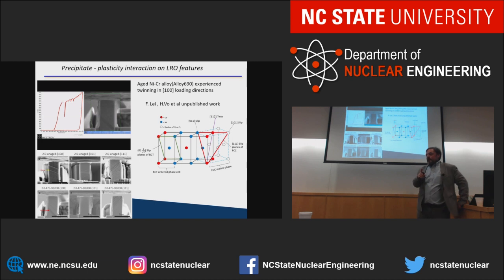Now that's not slipping, that's twinning. The crystal lattice changes by 60 degrees, changes the contrast, and you see that here in the still images too. You actually see the formation of twins, not these slip steps, which is different. So it turns out that if you compress your material in the 100 direction, in contrast to all the other ones, when they have those long-range order features, it changes from slipping to twinning. So which is an entirely different deformation mode, right? They don't have much in common.